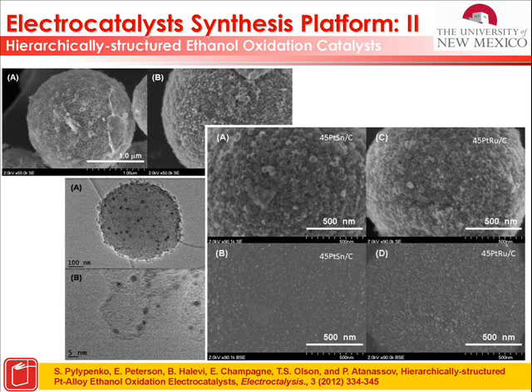The other thing which is extremely important for liquid fuel cells is to have an open pore structure, because if you really make a good catalyst, it will start gassing out. And once it starts gassing out, and if the gas is trapped in your anode, you are dead. You are dead because you're so good. So if you start making CO2, usually people who are beginners in DMFC experience a huge advance up to one point, and then they have a crash, and their crash is an engineering crash because they cannot outgas their anode.